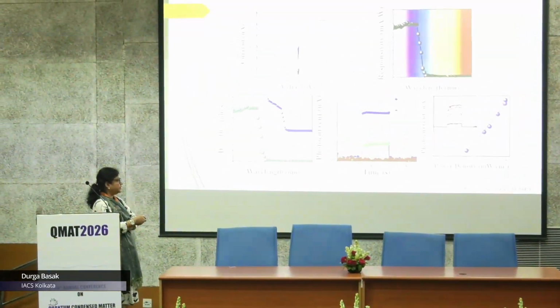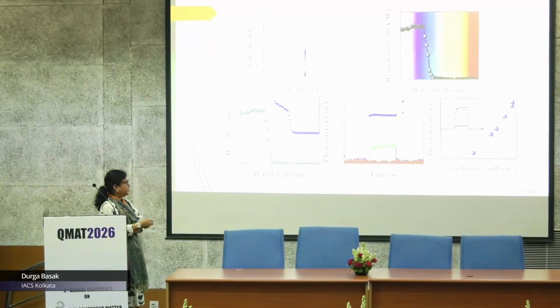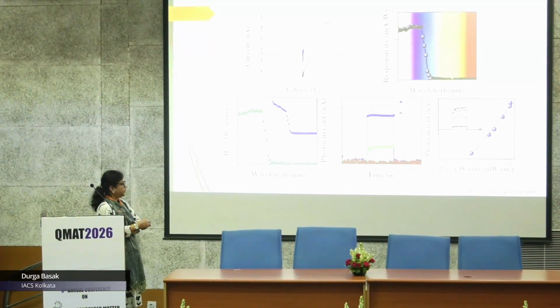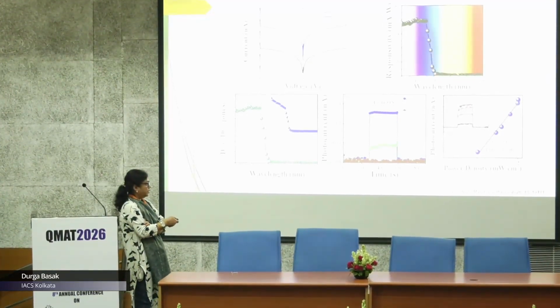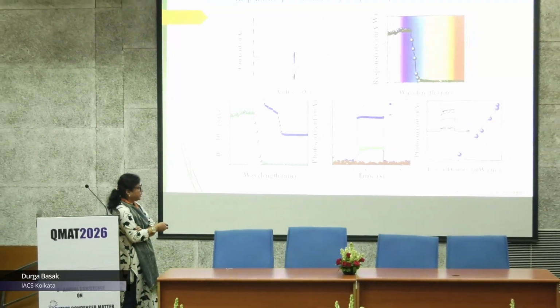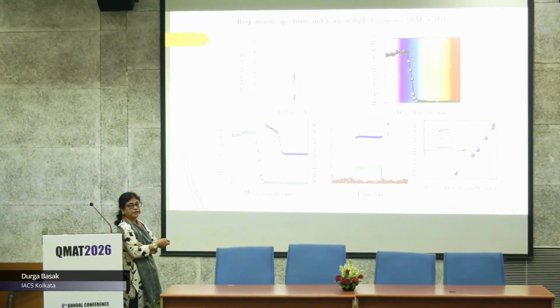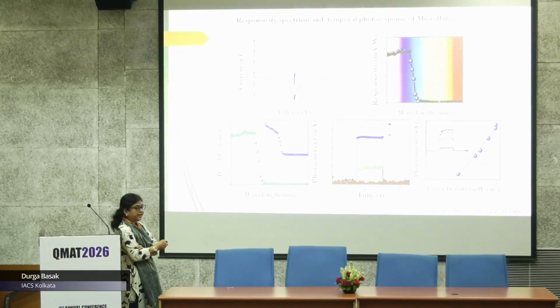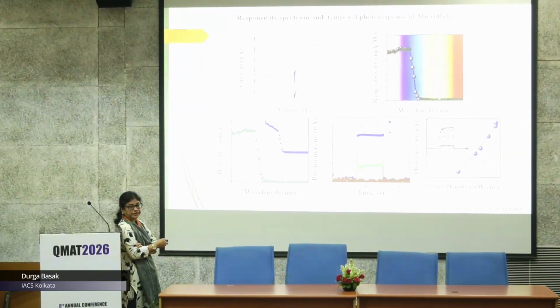So in case of microflake, we have done a similar experiment. The microflake is also equally responsive to 405 and 532, but surprisingly it doesn't show any response to 650 nanometer. It shows a rapid rise in the photocurrent for 532 nanometer and of course for 405 nanometer. Again we have plotted power density versus photocurrent, which shows an alpha value better than the single crystal. If you remember, it was around 0.8 and it is now almost 0.88, meaning it is much nearer to unit value.